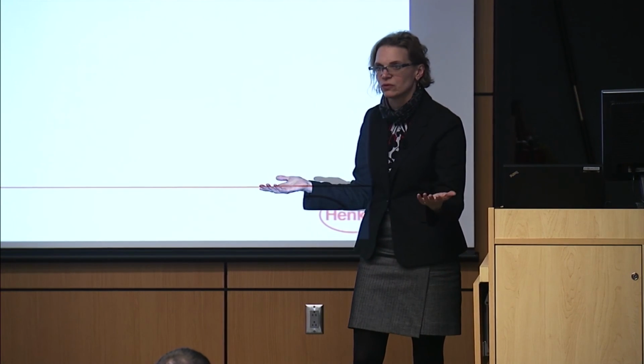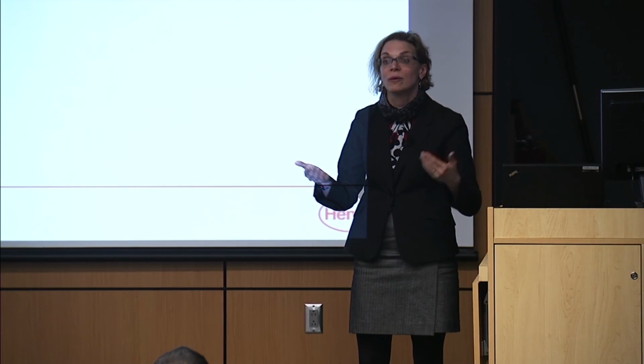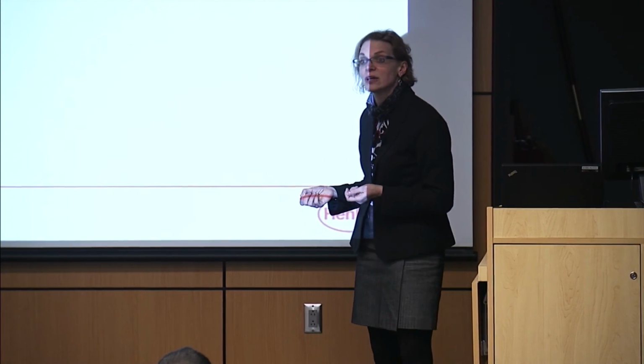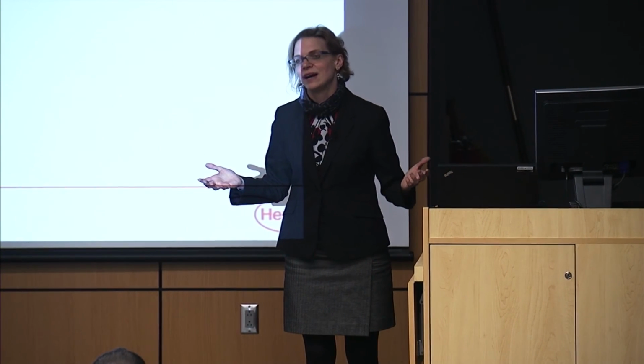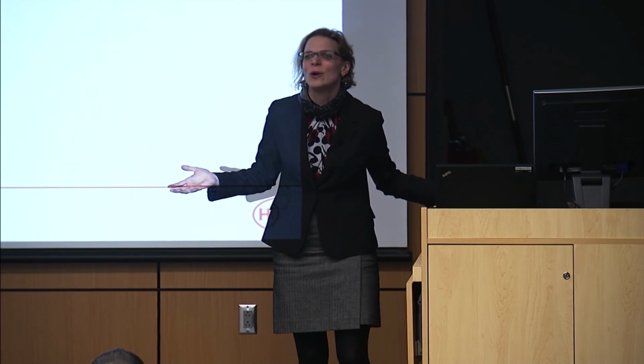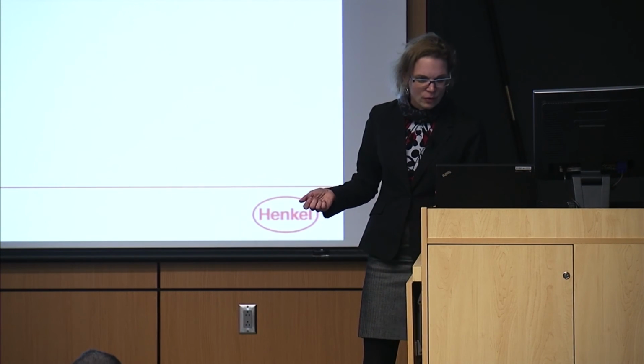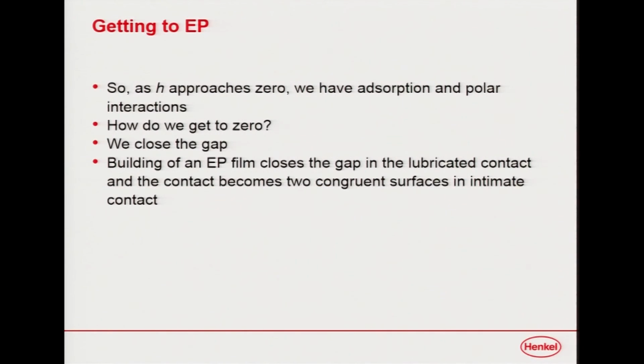And how do you get a transition state? You add electrons, typically to organic molecules, and you get some sort of transition state where you've got extra electrons, or you've opened up a bond somewhere halfway, and it's very, very reactive. So we've now figured out that there is some mechanical way to drive chemical reactions on these surfaces. And everybody kind of knew this was going on, but nobody knew how to talk about it even. So we get to this EP concept. We call it extreme pressure, and I really prefer to call it extreme temperature. So as H, that distance between the two surfaces starts to go to zero, you actually can generate some of these electrons, and you actually can generate these thermal gradients that you need to generate.